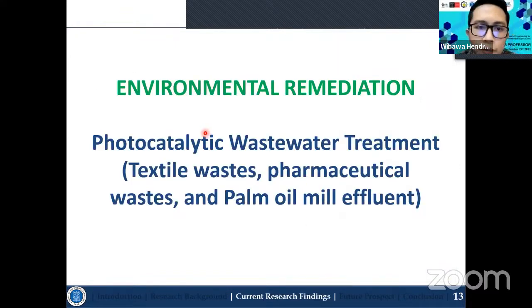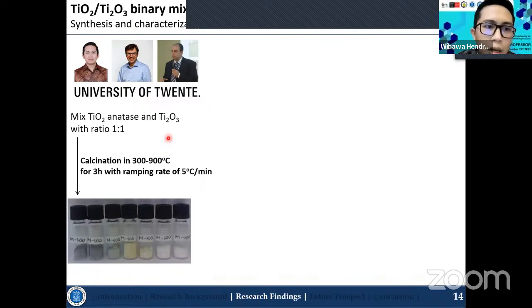Okay, so I move on to the first applications that our research group has reported. For these environmental remediations, I focus on textile waste, pharmaceutical waste, and also palm oil mill effluent waste. Starting from these concepts, I use the defect generation strategy where I create titanium 3+ in anatase titanium dioxide. The method to create these defects is simply mixing the TiO2 anatase with Ti2O3. The Ti2O3 here is not an active photocatalyst.